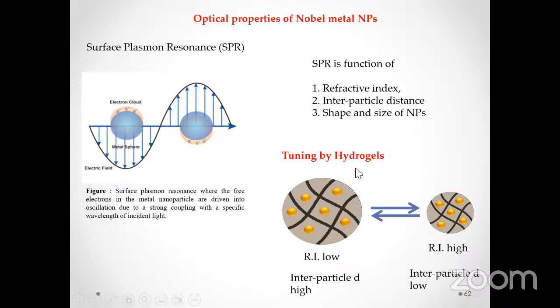So as I have discussed in the previous slides, we can control the shape or size of the nanoparticles just by controlling the mesh size. If we have a smaller mesh size, then we can prepare particles with smaller size, and smaller particles will have a different optical response as compared to those of larger size. And if we have prepared metal nanoparticles in a hydrogel system, then the optical properties of that system can also be tuned by just applying external stimuli. In this way, that system can be used as a sensor for external stimuli, such as temperature, pH, glucose strength, and various other parameters. As we can see over here, when this hydrogel system is in swollen form, the interparticle distance is large, and when the same undergoes shrinking, then the interparticle distance is decreased.